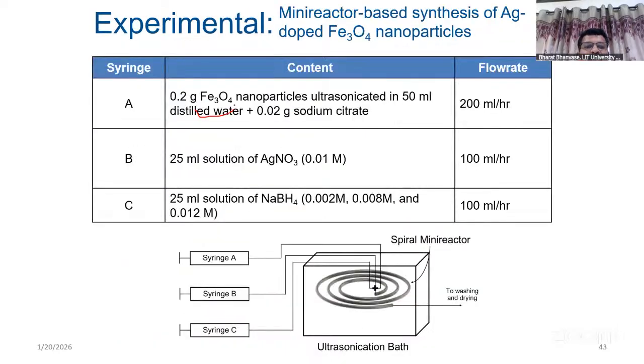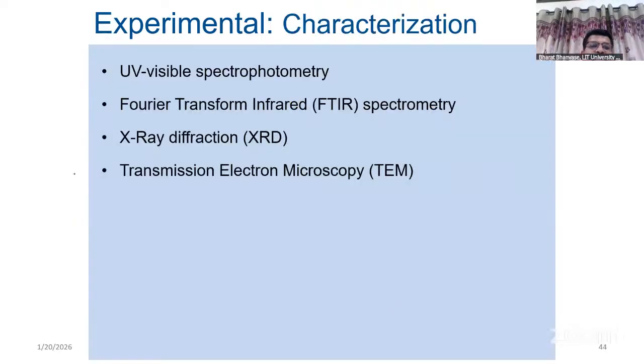In syringe A, we used 0.2 gram of Fe3O4 nanoparticles sonicated in presence of sodium citrate, with flow rate maintained at 200 ml per hour. In syringe B, we added AgNO3 solution, 0.01 molar, with flow rate 100 ml per hour. In syringe C, sodium borohydrate solution at different concentrations was tried, also at 100 ml per hour. So syringe A is Fe3O4 nanoparticle with surfactant, B is AgNO3, C is sodium borohydrate. As soon as these enter, reaction starts, and during flow crystal growth takes place, meaning deposition of Ag occurs, and by the time it comes out, the doped material is formed. This was characterized by UV-Vis, FTIR, XRD, and TEM analysis.